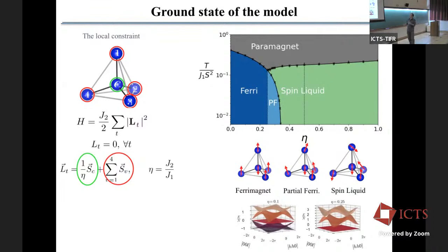If we calculate the bond excitations, on the left part of this phase diagram, the lowest band has dispersive bands, and the minimum corresponds to the ferrimagnetic states. But on the right part of this phase diagram, the lowest bands are these flat bands. And the thing is, the number of sublattices in this lattice is 6. You have 1, 2, 3, 4, 5, and the 6th one coming from the neighboring tetrahedron, because you have up tetrahedron and down tetrahedron. So you have 6 sublattices. 6 sublattices means that you have 6 bands. And here you only see 3 of them because the flat band is degenerate 4 times.